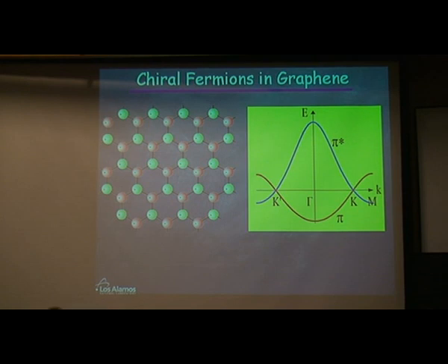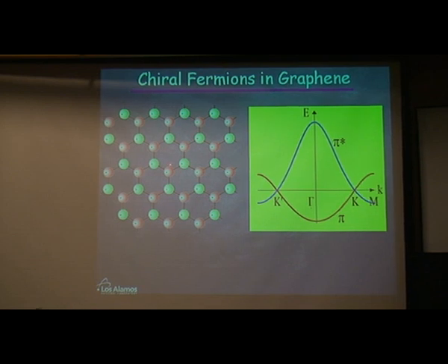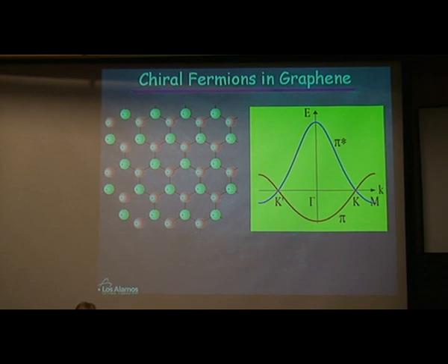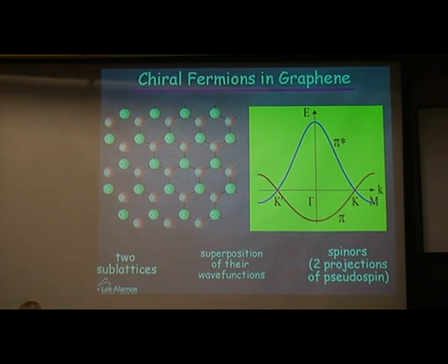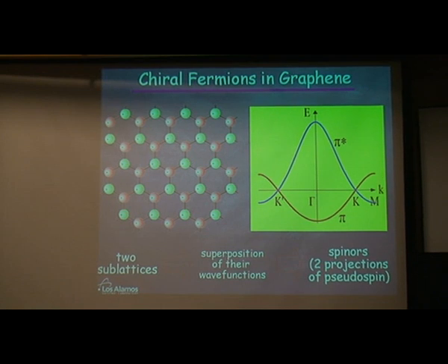But to build this band structure description, what we observe immediately is a bipartite lattice with two sublattices, red and green, or red and yellow. So the nearest neighbor hopping would be, in some tight binding approximation, some off-diagonal crosses. I have two components for two sublattices. So any electronic wave function of this lattice would be a two-component wave function. And that brings the spinorial nature of the excitation. You can call it a spin or pseudospin.